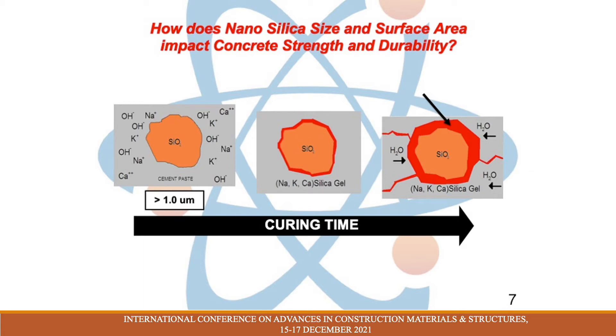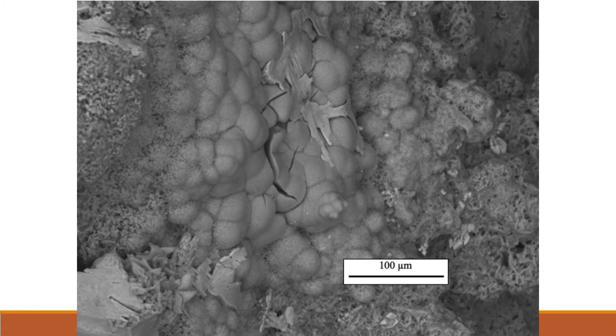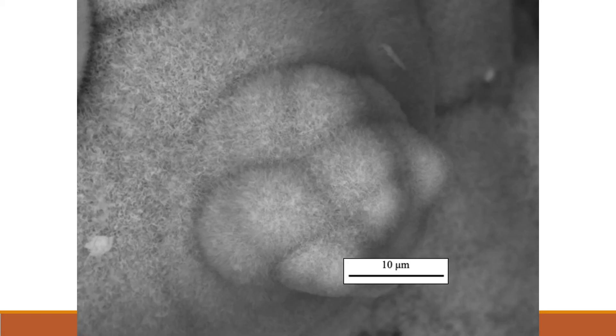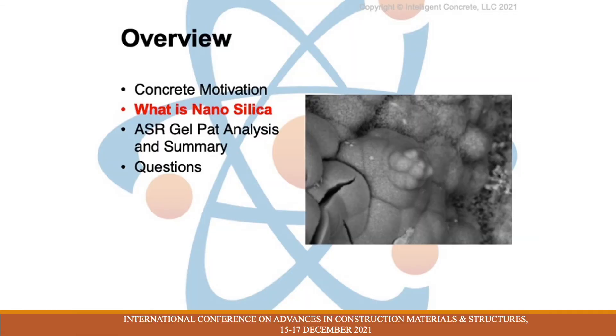Let's take a look at it under the microscope. Here it is in all its glory — the ASR gel rosette in a scanning electron microscope. Even closer, you can see those wispy-like fibers that make up not just the viscoelastic properties, but that phenomenon to imbibe more fluids, which will cause that expansion to thrive, survive, and continue to polymerize.